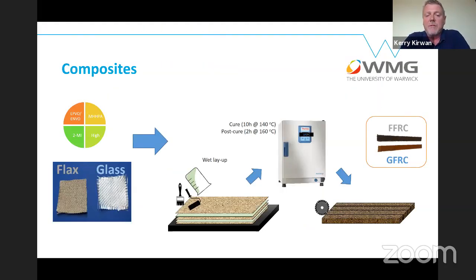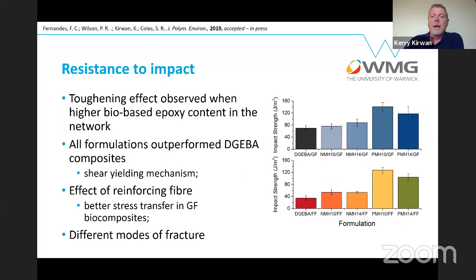So we moved on a little bit further, and here's the first composite layup picture that we've got. We took our formulation and we made some flax composites and some glass composites, quite traditionally by hand wet layup, cured them off, and then we tested them. And what we found was we did indeed manage to get this plasticizing, impact modifying property coming through from the bio-based epoxy. You can see in all instances, with the flax fibers and the glass fibers and the NMH10 and NMH14, the influence changing coming through there.